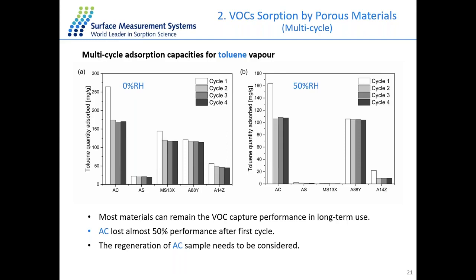This means that the charcoal sample may not be very good for long term use, and we need to consider regeneration of the charcoal sample after maybe one or two cycles, even though it has a very good performance in the first cycle. So in conclusion to this study, we can use DVS co-sorption to study the impact of background humidity on the performance of porous materials for VOC capture. It also shows a very different behavior compared to the single component result, which allows you to quantify the real world sorption behavior of this kind of industrial porous material.